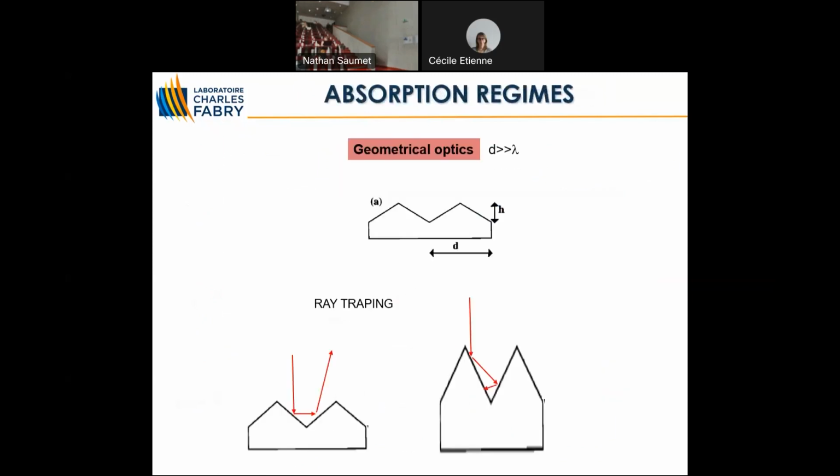So here the wavelength is much, much bigger than that. And therefore, you can assume that this grating is actually an effective medium with an effective index, just for the same reason that you are saying in the first place that your material is a homogeneous material, and you know this is not the case because it's made of atoms, and every 1 angstrom you have an atom, so it's certainly not homogeneous, but because the period, which is angstroms, is much smaller than the wavelength, you can assume that it's homogeneous. Well, this is valid even though the structure goes all the way to lambda divided by 10, roughly speaking.